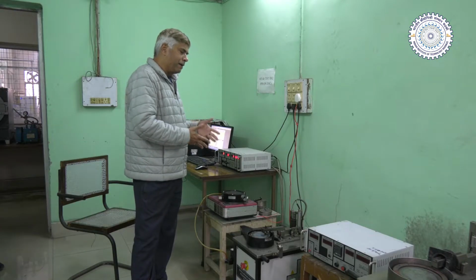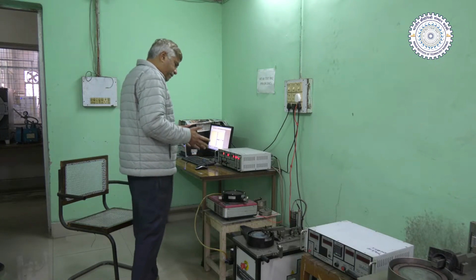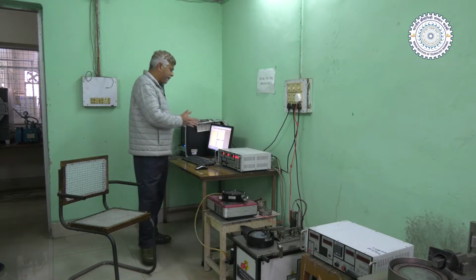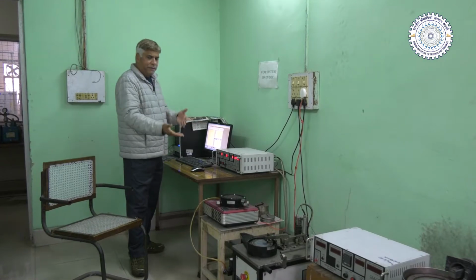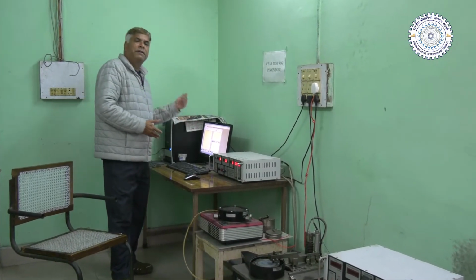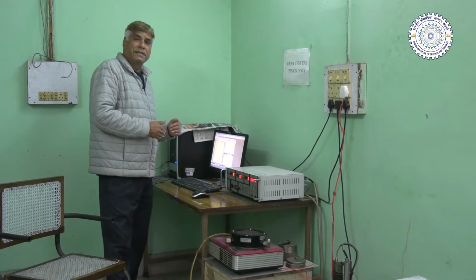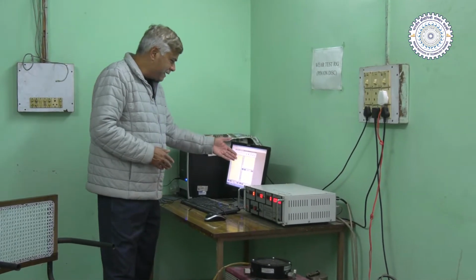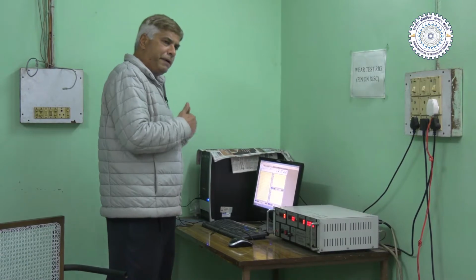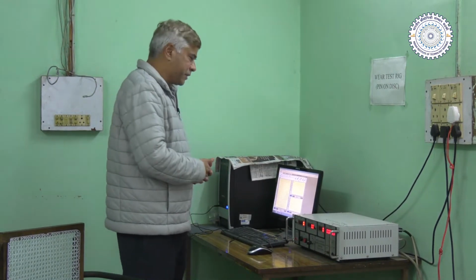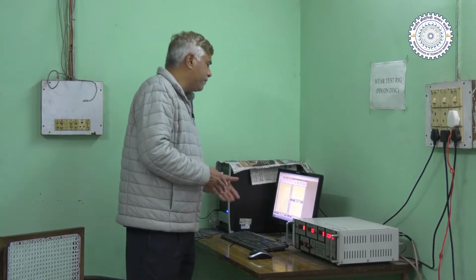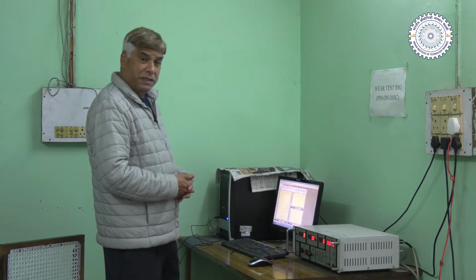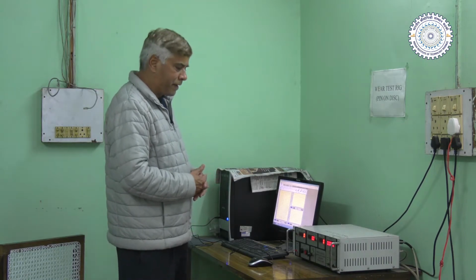And these parameters are basically acquired. We can see here one of the software with the machine itself, wherein we can see the wear in terms of the loss of dimensions, basically in micrometer, which is taking place. Then there is the friction force. It also measures and shows the variation in friction force as a function of the displacement or as a function of the time. Then there is also a window for showing the temperature as a function of the time during the test. So the friction, temperature, and the wear loss which is happening, all of those can be acquired and seen on a real time basis.